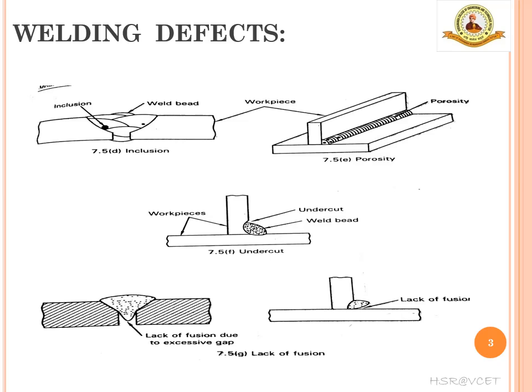The next defect is undercut. Undercut, the worst of all defects, is the term given to the sharp narrow groove along the toe of the weld due to the gouging action of the arc, removing the metal and not replacing it with weld metal. As you can see in figure 7.5F, on the vertical weld plate, there is a small groove which has not been filled by the weld metal. Causes are high voltage and welding current, high arc travel speed, incorrect electrode manipulation, and arc gap too long.